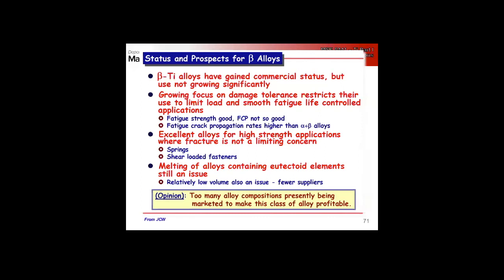Is that just because 6-4 can be cast and then you don't have to go through all the thermomechanical processing? Well, it's just because the traditional application for titanium is high specific strength: high strength, low density. And the alpha plus beta alloys give you that easily. Plus, you have better creep resistance, better high temperature performance. So if you think of what the traditional use case for titanium was, the alpha plus beta alloys sort of fit.